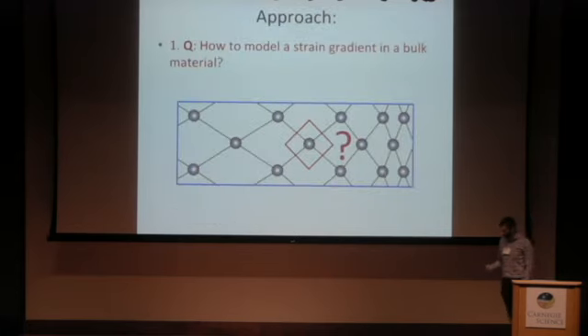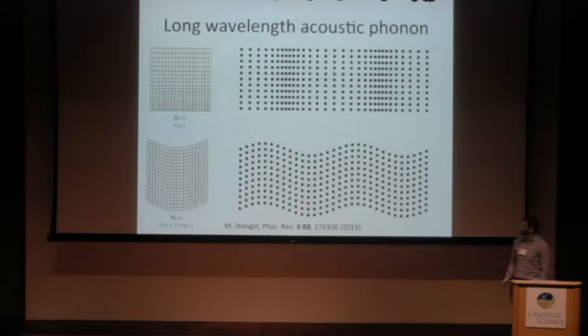So the first question that we have to answer is, how do we model a strain gradient in a bulk material? It's not even obvious, since we've broken the translational symmetry of our crystal with a strain gradient, how to define a unit cell. So the approach to doing this is to realize that we can identify the different types of strain gradients in different types of acoustic phonons. And so if we treat a strain gradient as a very long wavelength acoustic phonon, then we've recovered the periodicity that's necessary to do a bulk calculation. Of course, we don't want to try to create a supercell that will capture this long wavelength periodicity, but thankfully we don't have to.